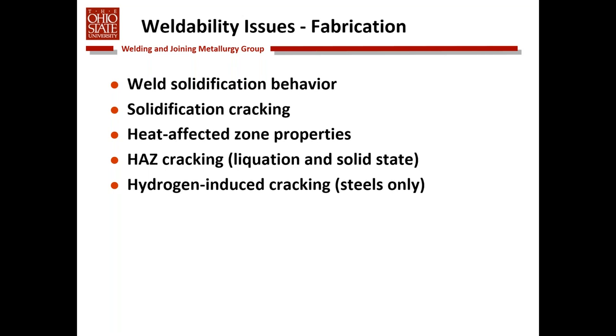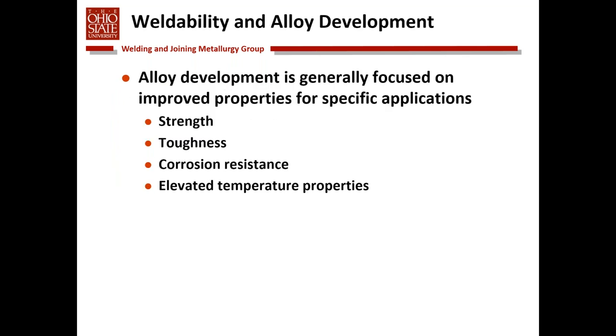And then, of course, there's hydrogen induced cracking. This is primarily associated with steels, can occur in other materials, but normally high strength steels are those susceptible to hydrogen induced cracking. So these are the main weldability issues that we deal with from a fabrication standpoint, and around which a lot of weldability tests have been developed.